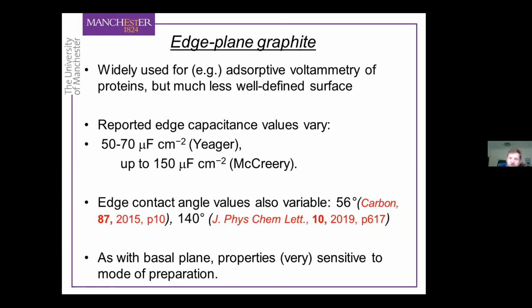For example, if you look at the capacitance values quoted for the graphite edge plane, using two of the names I've already given, Yeager and McCreery, Yeager gives values of about 60 microfarads per square centimeter, whereas according to McCreery, the edge plane capacitance is more like 150 microfarads per square centimeter. So there's a huge disparity in the reported values.